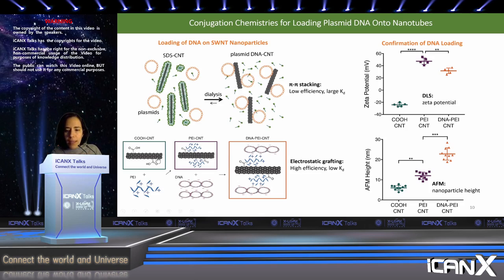On this second chemistry that we developed, we first carboxylate the surface of the carbon nanotube, and then through an EDC-NHS reaction, we can attach a cationic polymer, such as a branched polyethyleneimine, to these carboxyl handles. These PEI functionalized carbon nanotubes now carry a positive charge that can load DNA plasmids through electrostatic interactions between the positive carbon nanotube and the negatively charged DNA. These electrostatic grafting interactions have a high affinity, a much stronger bond than pi-pi stacking interactions. So plasmids are loaded tightly and have a low dissociation constant.